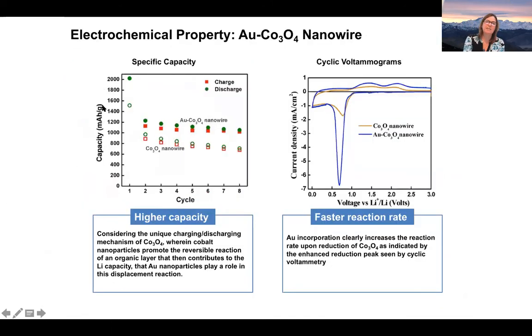Now we're looking at capacity again versus cycle, and this is our 1 gene battery here for just cobalt oxide, and now we have cobalt oxide and gold, and we get a higher capacity, we get better cycling and a faster reaction time. And so it was all based on being able to control DNA sequences that code for these different protein sequences, where these protein sequences could simultaneously grow 2 different materials, 1 good ionic conductor, 1 good electrical conductor.